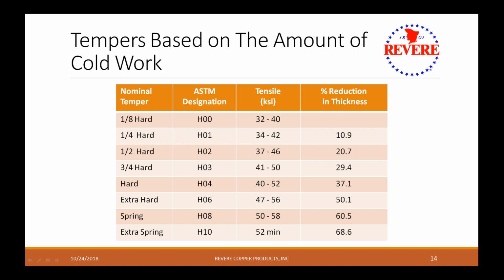So for example, a roofing copper would be ordered generally at quarter hard, because you want the hardness, you want it to be resistant to dents if it's going to go on the roof, but you need it ductile enough to be able to form the seam. So this is an example of different hardnesses for hard metal that's ordered, and the key to getting that property is a % reduction in thickness after the last anneal.